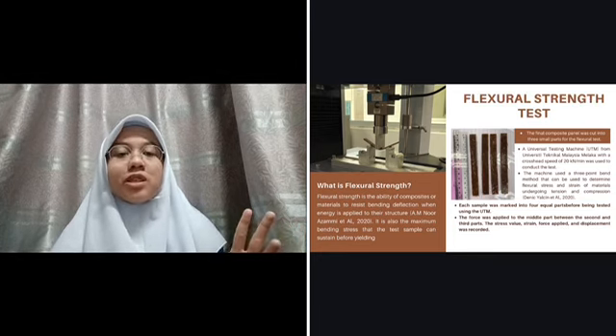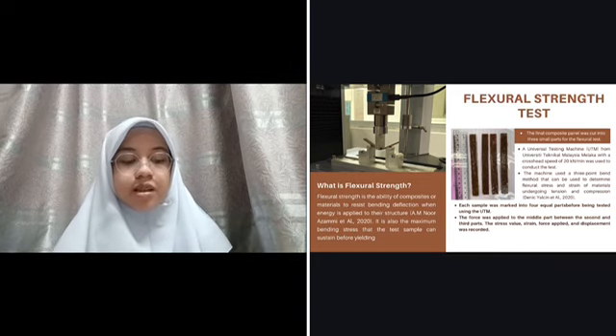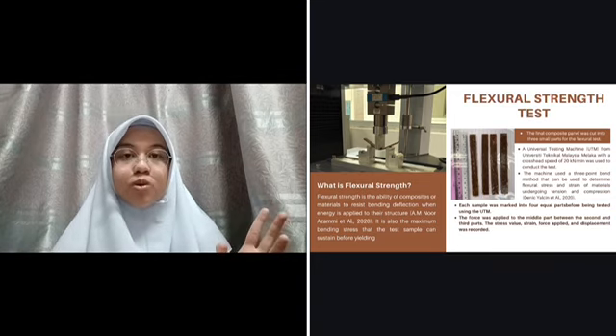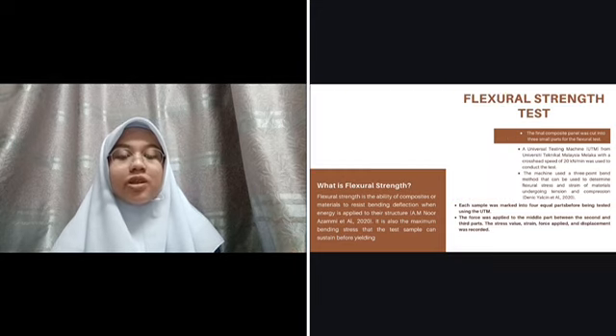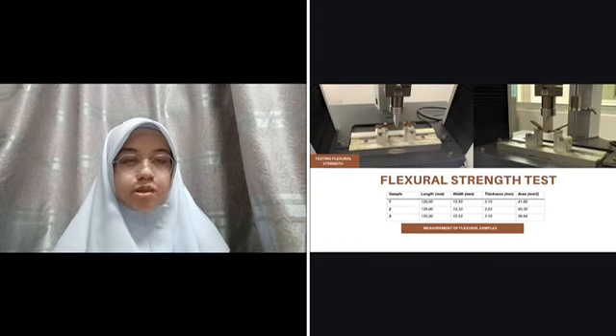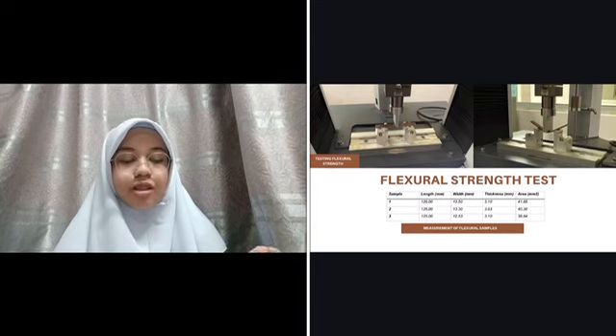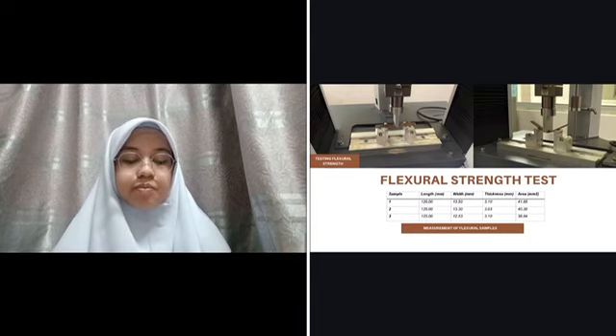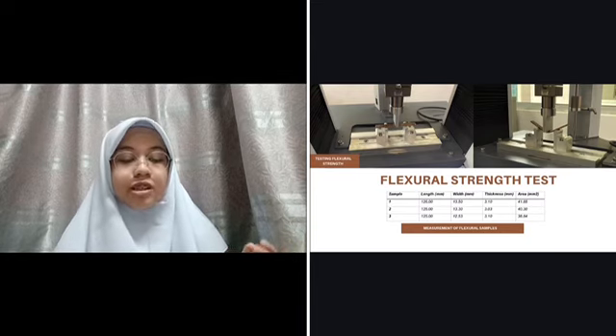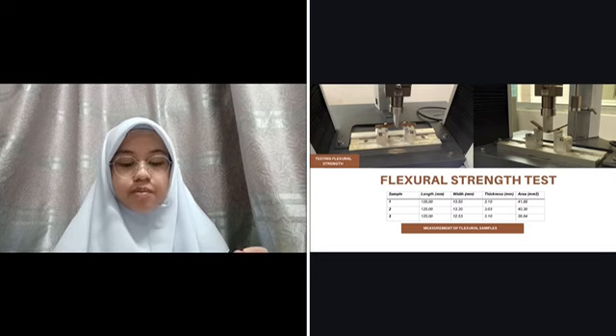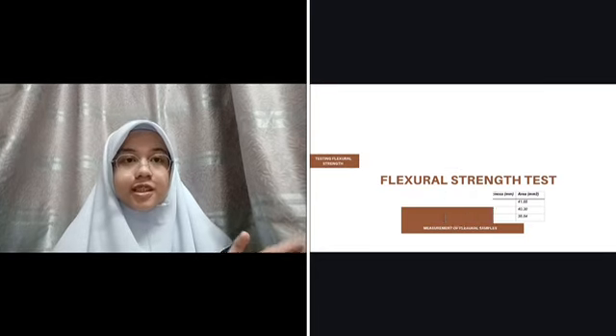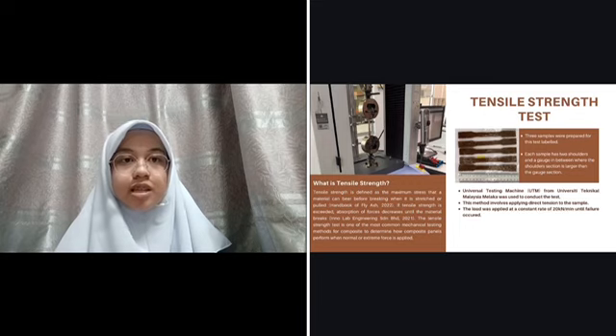We used 3 samples for this test where each sample was marked into 4 equal parts. Here are the measurements of the flexural samples. As we can see, the width, thickness, and area of each sample are different, whereas the length of each sample is slightly the same.